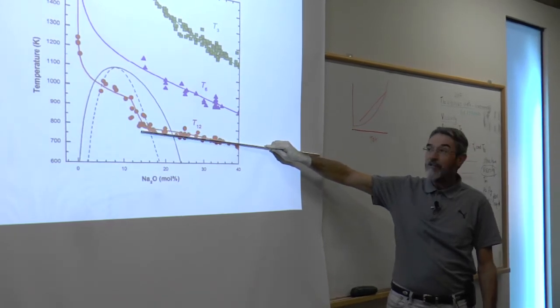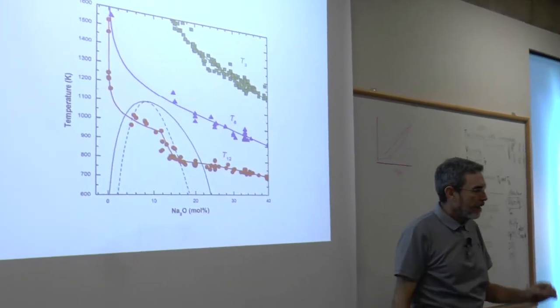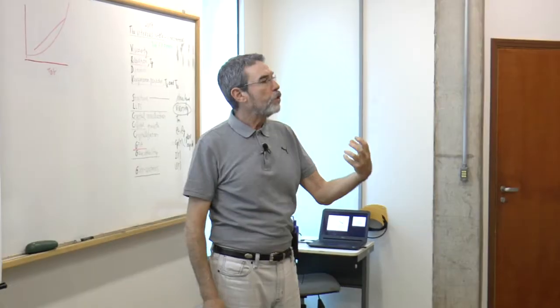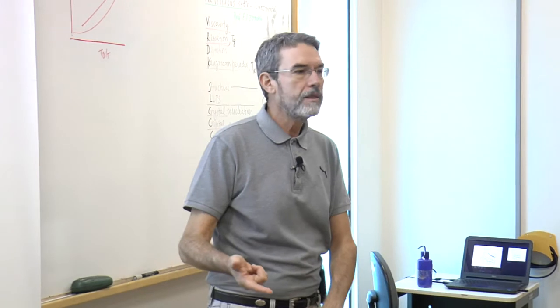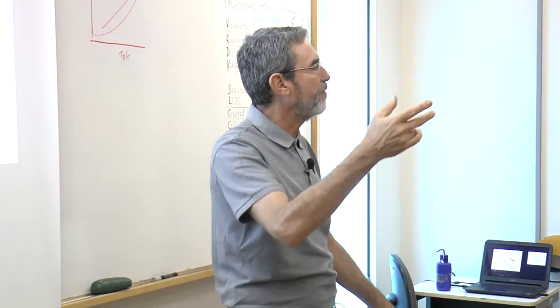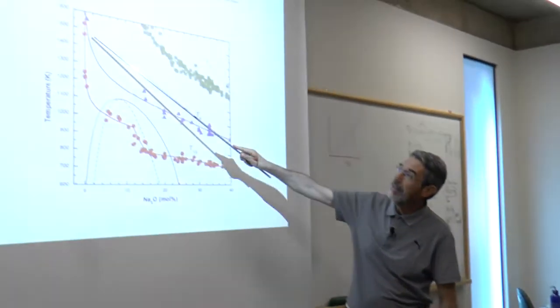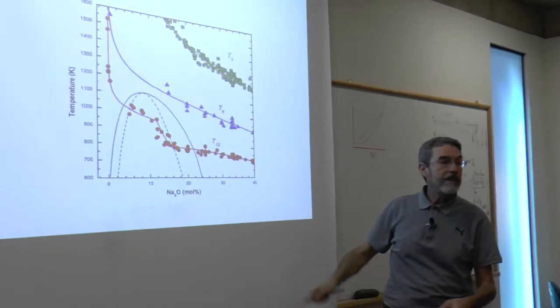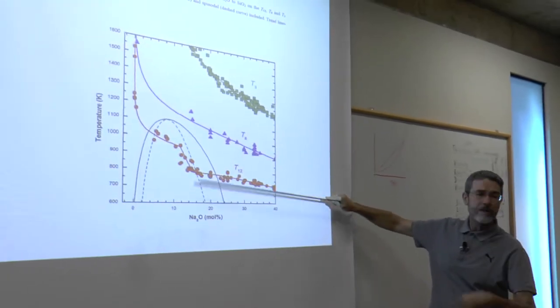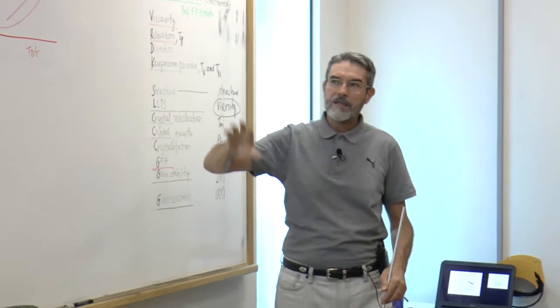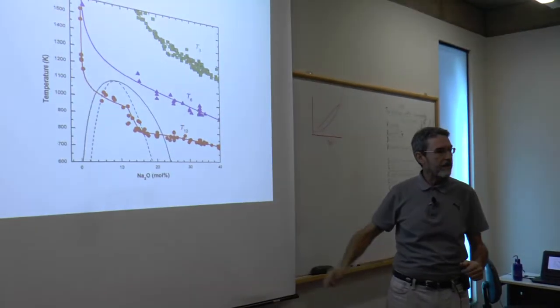And that's why it's very difficult to reproduce pure silica glasses. Pure silica or pure germania or pure P2O5 or pure TeO2 or pure B2O3, pure oxide glasses are extremely difficult to reproduce. Every time you make one, you come up with different properties because every glass has a small amount of this, a small amount of that, small amounts of different elements. It's a huge effect with very small quantities of these elements and also of water. Now, if the structure is already broken, we are going to talk about glass structure in a few weeks, and you will see exactly what happens. This is a striking plot, and I like it very much because it shows the nature of the glassy state.